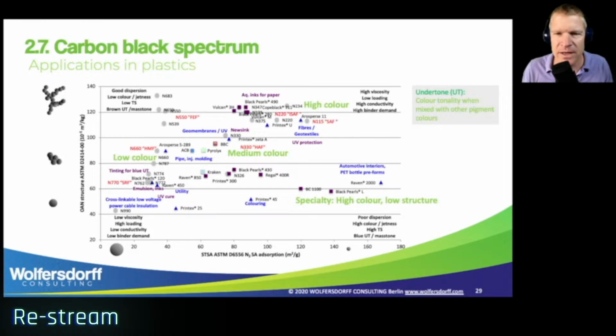We have the 200 range of rubber blacks, which on the plastics side of the world are called ISAF, intermediate super abrasion furnace. Or we can have the N100 type of rubber blacks, which are called super abrasion furnace. And you can see at the edges of this chart the effect of going higher structure, bigger particle or smaller particle. And one of the problems is if you go high color and we have a high structure, we get high viscosity and we're limited in the loading.